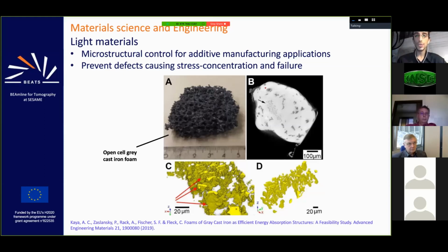So in this case, synchrotron computed tomography was used to study the nucleation of different phases in the metal phase itself, as well as to control for the foam properties, so connectivity and defects in the foam, which at the end of the day will determine the failure properties of the foam, because defects act as stress concentrators. So at the end, it is where the fracture will start. So to control and check the fabrication process in 3D at high resolution is very important to actually determine the final mechanical performance of the material.